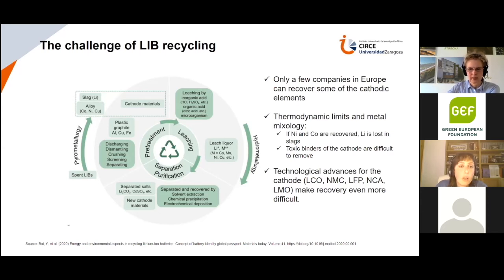go with the hydrometallurgical steps, and this route would be carried out through leaching by inorganic acids to facilitate metal recovery from dissolved metal solutions. And this obviously requires the introduction of expensive and toxic materials. And after that, it follows the final step, which would be separation and purification through different techniques, such as solvent extraction, chemical precipitation or electrochemical deposition. And well, we have different challenges.